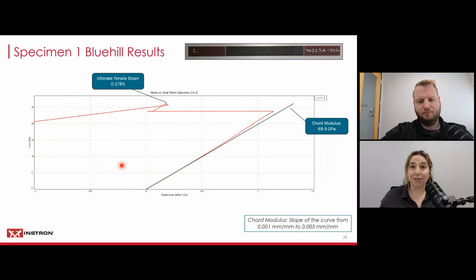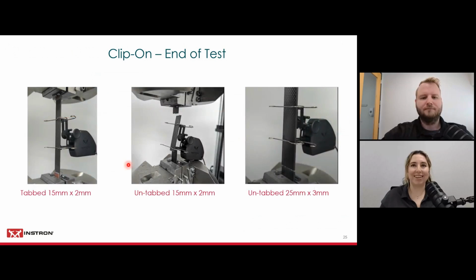For my second specimen, it was a high impact break. It broke just outside of the jaw faces, and thankfully my grips caught my extensometer before it completely fell. And then my last one, my largest tab specimen, did have a break just outside of the jaw face, and was also a high force break, and we were able to maintain contact throughout the entirety of the test.